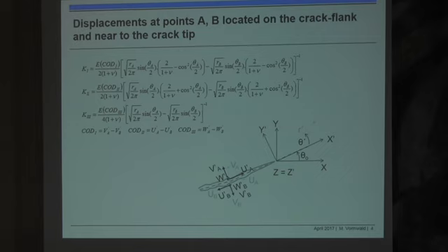So we have all these time steps where a snapshot was taken of the deformation field. We have now calculated values of that. However, keep in mind that in these measured values, CODs, if there is some plasticity around the crack tip, then it is incorporated in a certain sense in those values. And if there is crack closure, and there is crack closure, then these calculated K values are also plasticity and closure corrected K values, not strictly those from linear theory of elasticity.